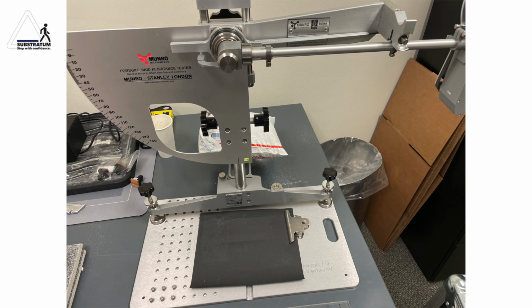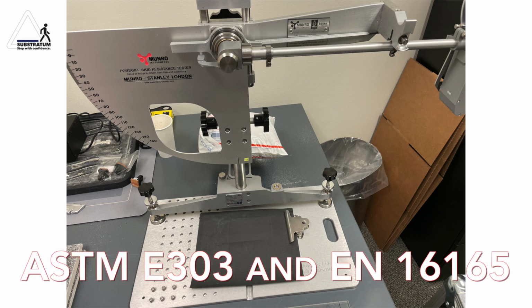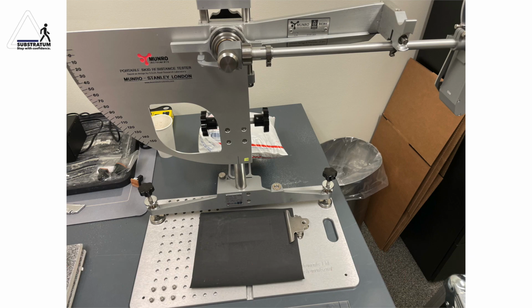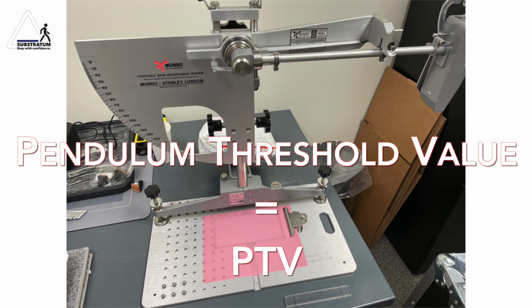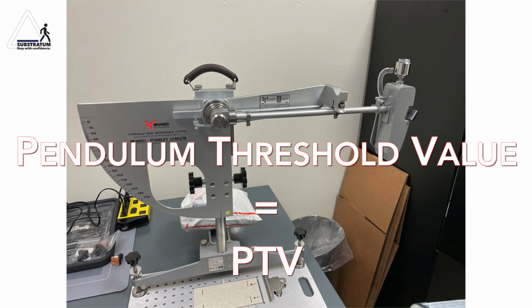There are several standards for using a pendulum, including ASTM E303 and EN16165. The standards outline 3 reference surface materials that ensure the pendulum is working correctly. Pink lapping film, float glass, and tile provide specific pendulum threshold values, or PTV.